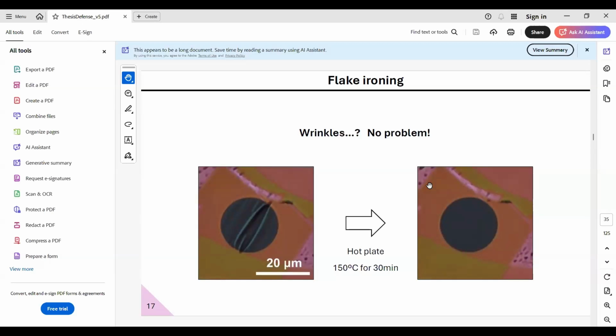So I was trying to understand this. The circle here is suspended, right? Yes. Okay. So you basically found that if you heat it up on a hot plate, the transferred film becomes smooth, right? Yes. So two questions about this. One is when you heat it up, is it in air or is it in a glove box, or what's around it? It's air. Okay. And does the material degrade if you heat it up in air at 150 Celsius for 30 minutes? That we don't know, but as it stays suspended, I believe the crystal is undamaged. But of course, we can compare before heating, after heating, if the material changes.